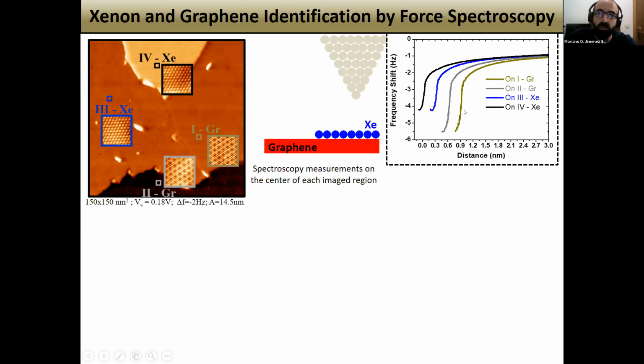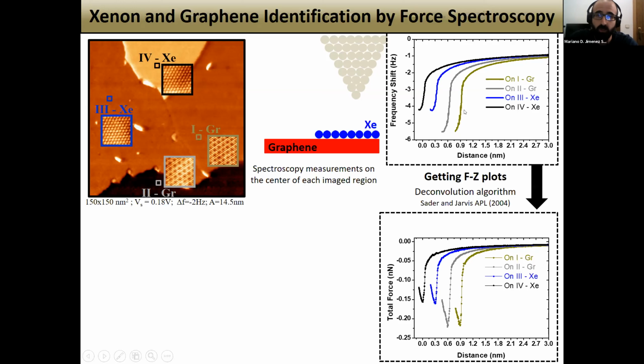But what about the force? Well, we can get the force distance plot by means of the deconvolution algorithm of Sader and Jarvis, giving rise to these curves. This total force distance curve has two components. A first component related with the long range van der Waals interaction, and a second component related with the short range, which gives us information about the chemical species which are below the tip. And we are interested in this one.